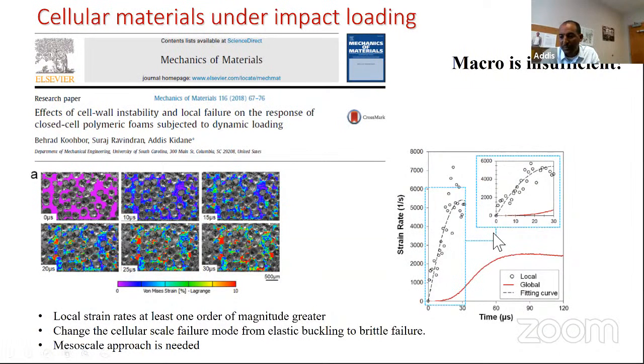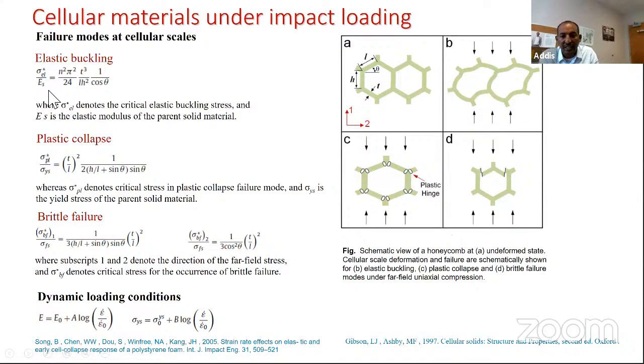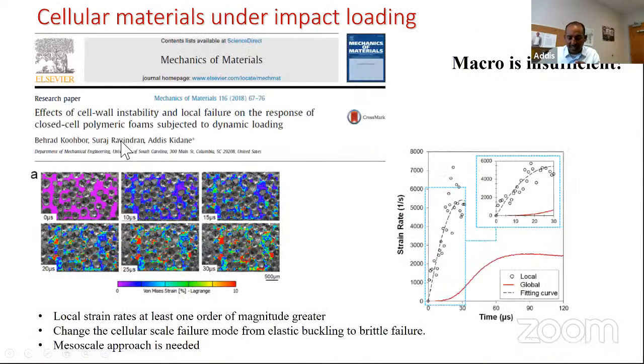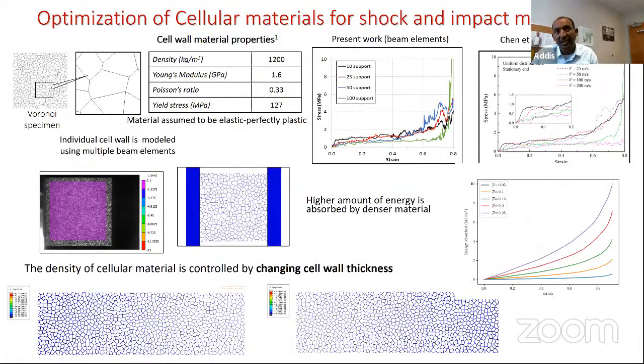So if the strain rate response is this much different, you cannot just simply update the strain rate of the parent materials and use it to find the local response of these materials. This tells us we need another way to understand these materials under high strain rate loadings. So we started our own finite element models using these cellular models, Voronoi models. Our objective is to understand this material and its response and try to optimize its configurations, in order to absorb more energy when subjected to impact as well as shock loadings.